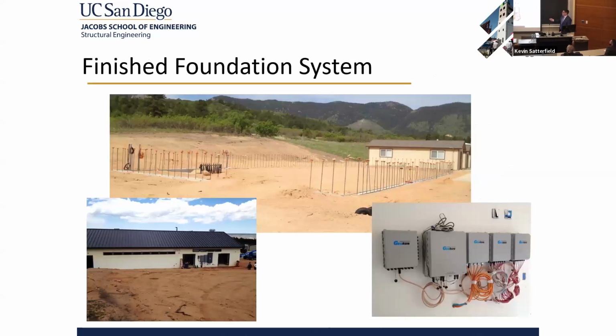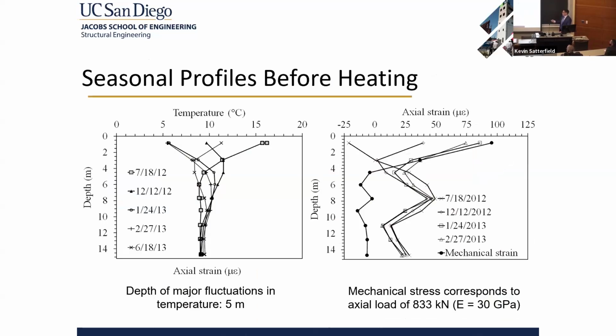This is what it looked like afterwards. We had a 3-foot grade beam, which added to the strength. And then we waited some time for the concrete to cure. We were able to get the temperature profile at the site over the seasons, and the temperature and strains during curing.